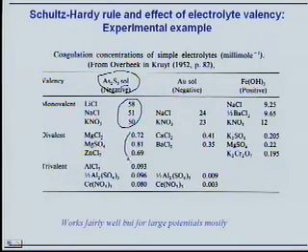If you use divalent ions, again you can see that the concentration that you need to use is not so much dependent on the ion. So you can use magnesium or zinc, calcium in many cases. It's about the same. But then the relation between the monovalent and divalent is enormous. You have 2 orders of magnitude difference in the concentration that you need.